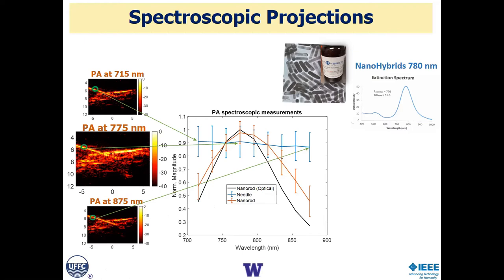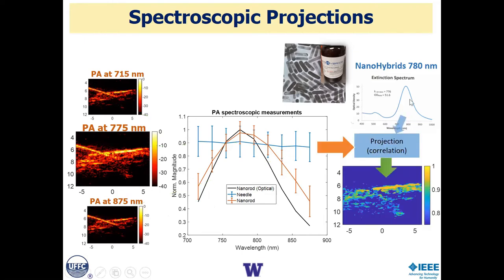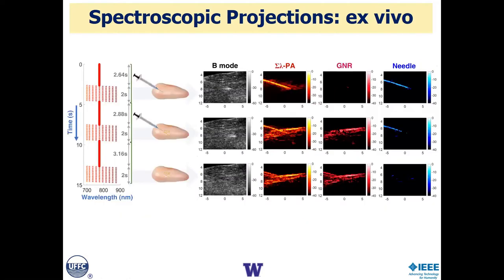So what does that allow us to do in this imaging format? It allows us to make projections of the measured photoacoustic spectra onto the expected spectra of absorbers in the image. In this case, which is the simplest example, we have two absorbers. One is the contrast agent and the second is the needle. So we can make images which separate those two. And that's shown here. So here's the sequence through this experiment.